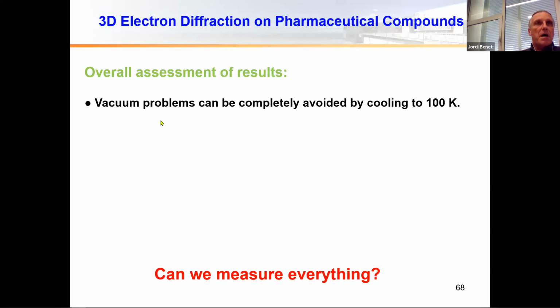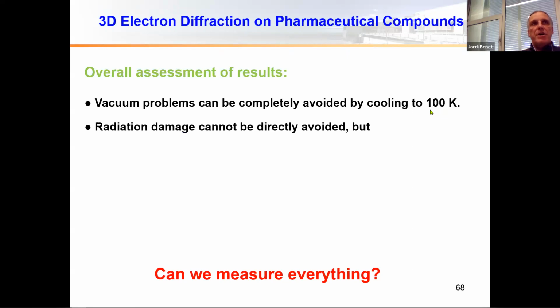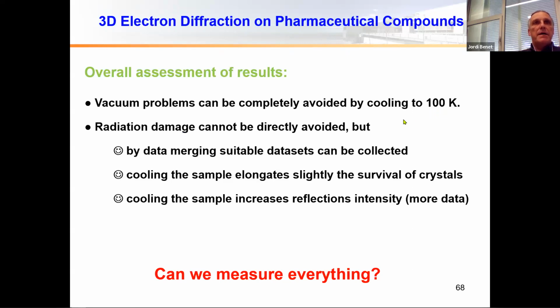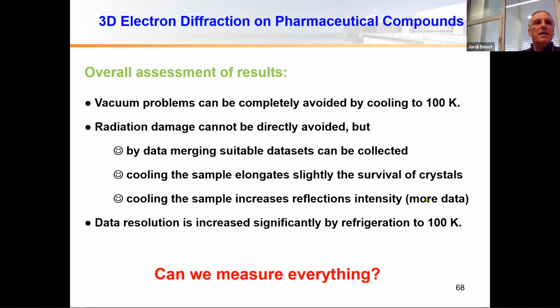So vacuum problems, I think, can be completely or maybe close to completely avoided by cooling to 100 Kelvin. Radiation damage cannot be directly avoided, but we can merge data sets and collect short crystal series. We can cool the sample and get, let's say, a bit longer survival of the crystals. And third point, we can cool the samples and increase the reflection intensity so we can collect more data. Finally, data resolution is increased significantly by cooling down the crystals. So this is a clear answer to the question, is it necessary to cool down?